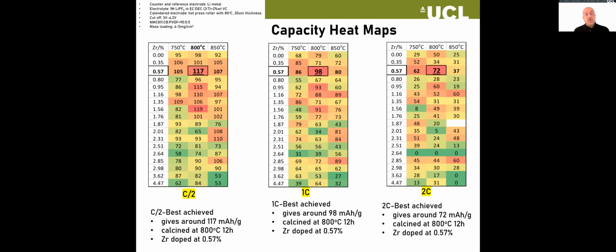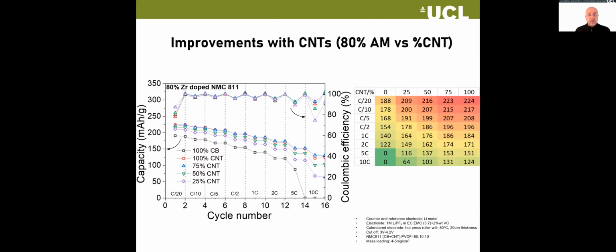As we charge and discharge much quicker, it turns out that the champion sample is the 0.57% zirconia doped NMC material, which is of course replacing the manganese, I should say. What we're trying to do here is identify which is the best sample for high C rates. The next step really is to try and engineer the electrode to make it more conductive and perform better. So this was our next step. I'll just highlight those points.